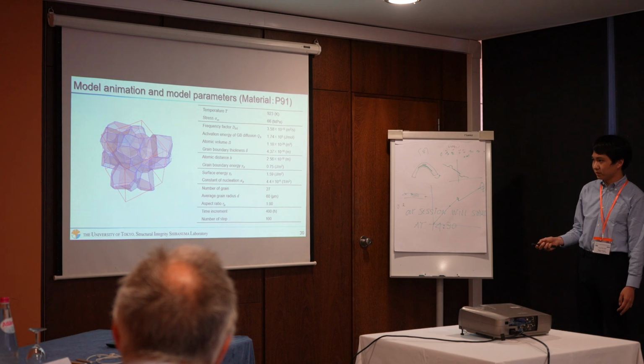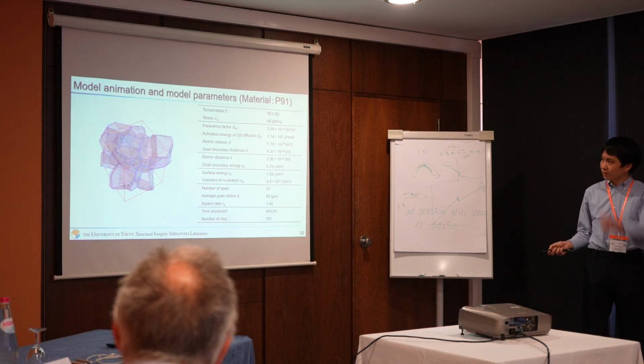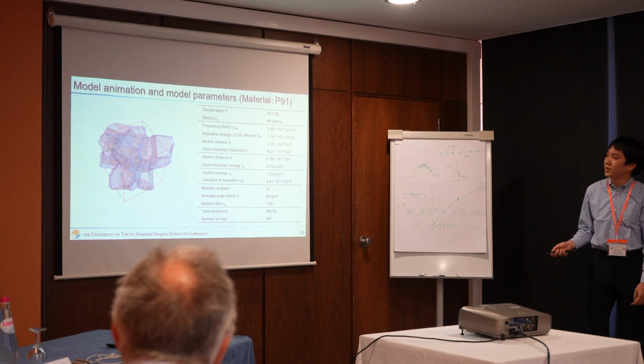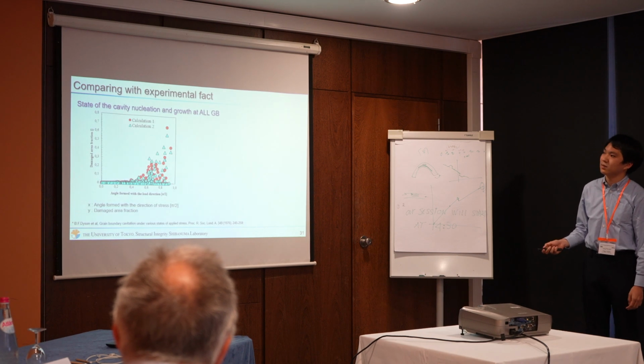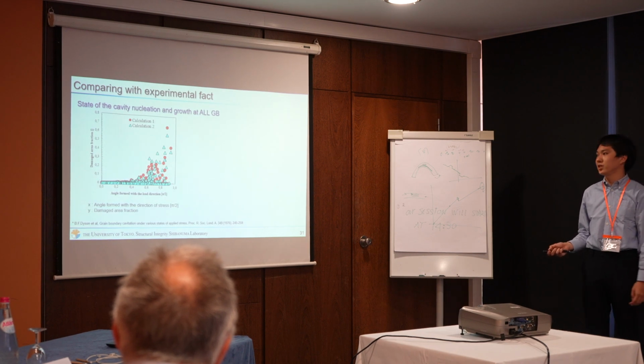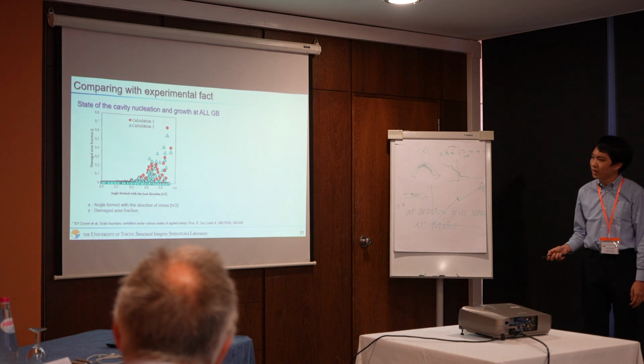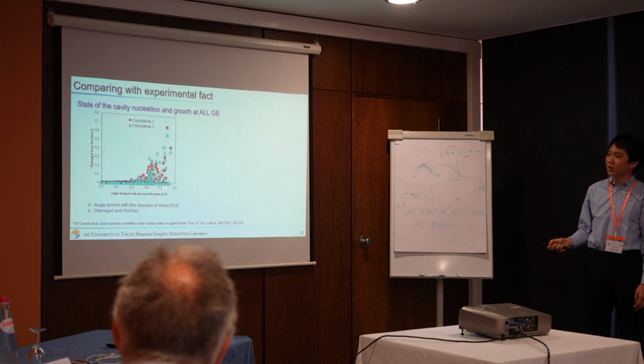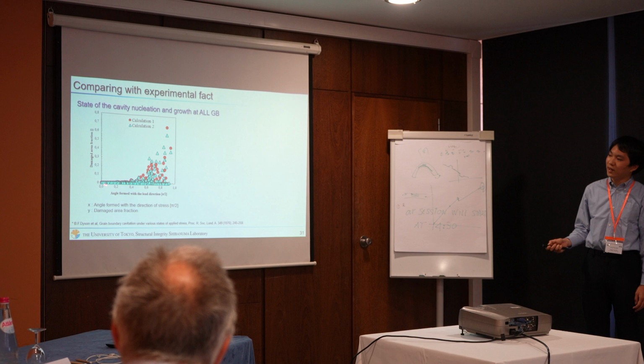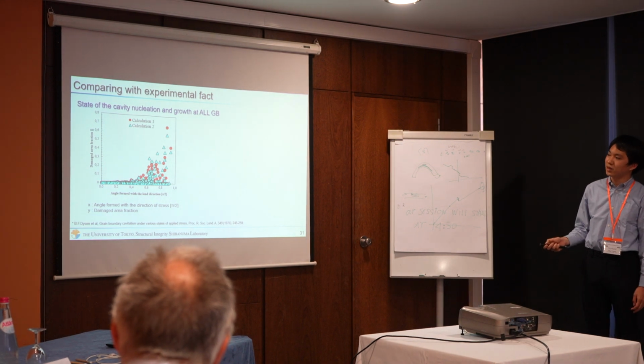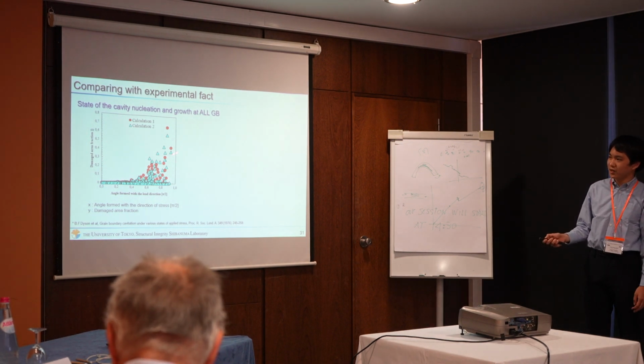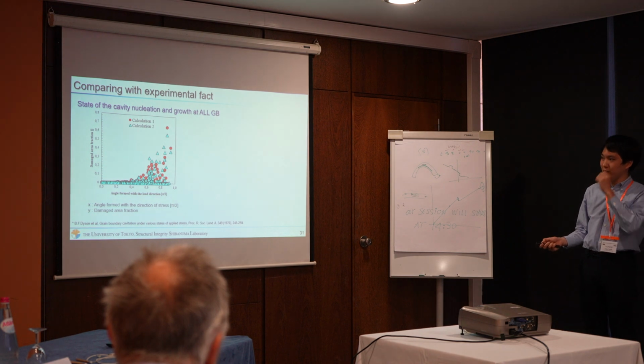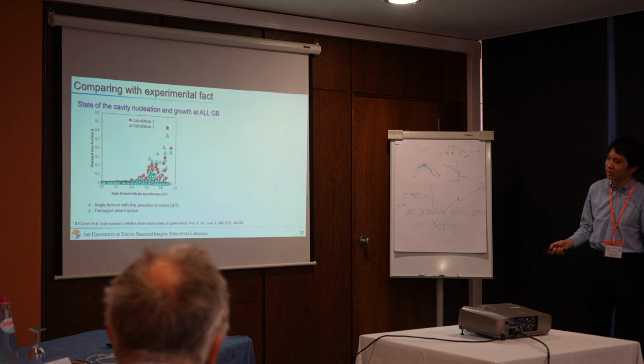This is the calculation example. This parameter is also P91. And this is the state of cavity nucleation and growth at all grain boundaries. The x-axis is the angle formed with the load direction. The y-axis is the damage area fraction. Damage area fraction is higher at the grain boundary perpendicular to the stress direction.